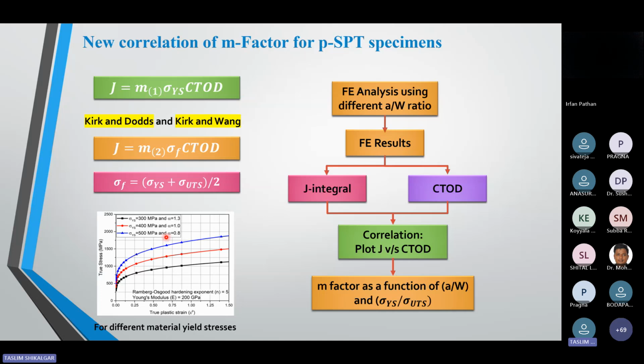Maybe you know that the power law equation is the famous K epsilon_p raised to N. Similarly, another equation is available, the RO equation, known as the Ramberg-Osgood parameters. There is also one alpha that is important and one N that is important. I used this RO equation to generate this type of data, and I also varied N. N is the hardening exponent.